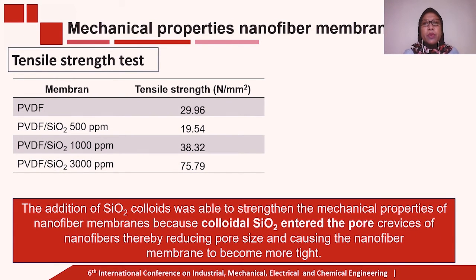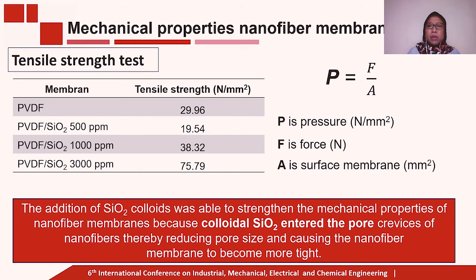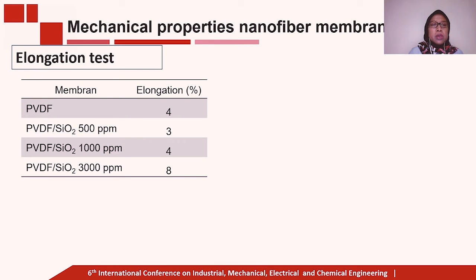Next is mechanical properties of nanofiber membrane. First, tensile strength test. The addition of SiO2 colloid was able to strengthen nanofiber membrane mechanical property because colloidal SiO2 enter the pore crevice of nanofiber, thereby reducing pore size and causing the nanofiber membrane to become tighter. This is the equation.